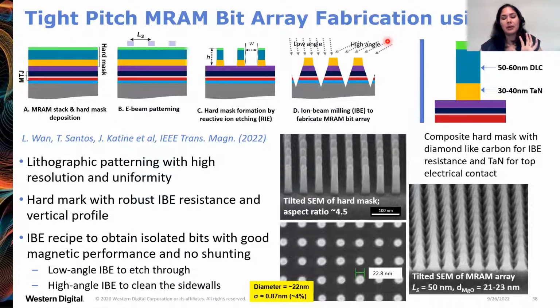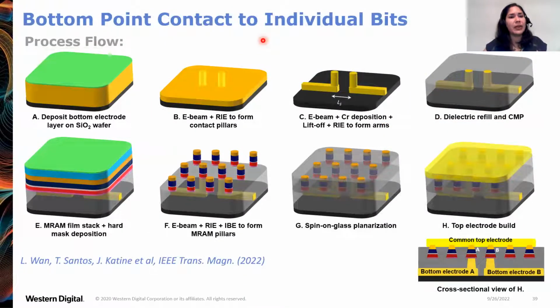Remember that the wafer is rotating during this process to mill away the redeposited material on the sidewalls to prevent that shunting. And so here's a tilted SEM image of the final tight pitch array after milling. But now we want to do electrical measurement, and we don't have easy access to very expensive CMOS. So we do the best we can in our research lab, and we came up with a bottom point contact vehicle so that we could electrically measure these bits.